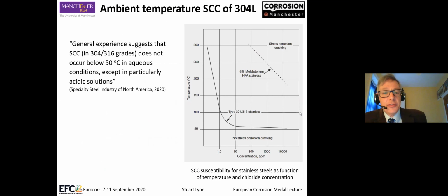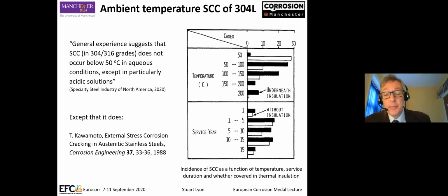So moving on a little bit further, now on to still passive materials. This research came out of the nuclear industry, where they're interested in retaining nuclear waste in stainless steel containers for forever, essentially. And they were running with this comment, which is very, very common: general experience suggests that SCC of stainless does not occur below 50 degrees, except in particularly acidic conditions. And this is still being stated by the SSINA in 2020 on their website. And that's a wonderful thing if it was true. Unfortunately, it's not true. It does happen.